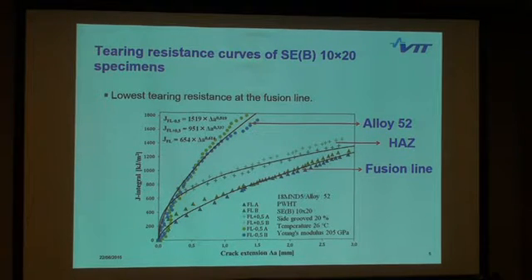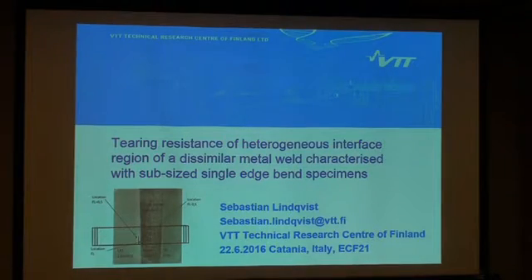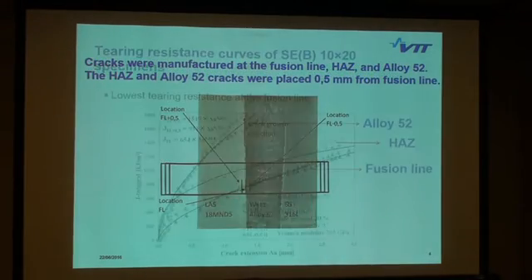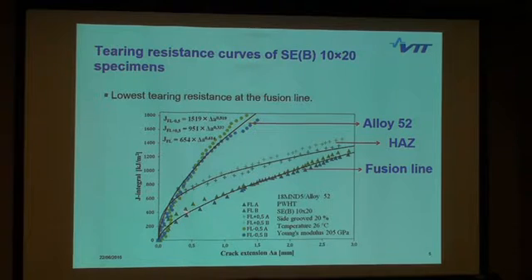So let's start with the 10 times 20 single-edge bend specimens. These results seem to be quite consistent. The two specimens tested at the fusion line follow this line, and then the cracks manufactured at the heat affected zone follow this line, and the alloy 52 tearing resistance is seen from here. These results can be thought of as reference results.